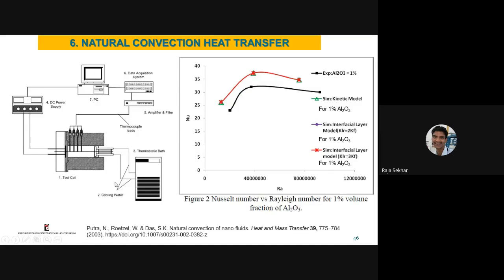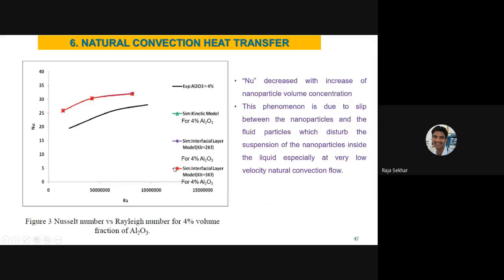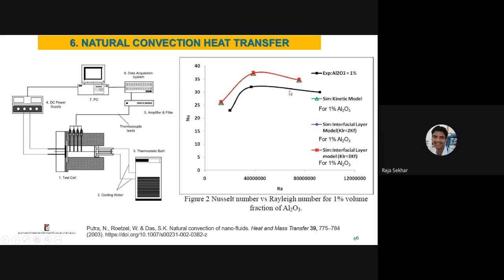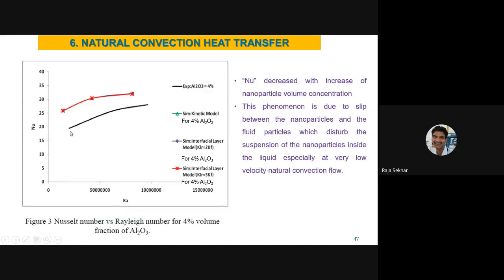This is the experimental setup that people have used to conduct the natural convection test. And you can see this is the trend for experimental values. It is from 20 to 30 for 1% volume concentration. For 4%, you can see it is further reduced. So the more concentration you add in natural convection, the Nusselt number or the heat transfer rate is decreasing. So the Nu is decreasing with increasing particle concentration. The reason that people have given is the slip between the nanoparticles and the fluid particles, which disrupts the suspension of nanoparticles inside the liquid, especially at very low velocity happening under natural convection flow.